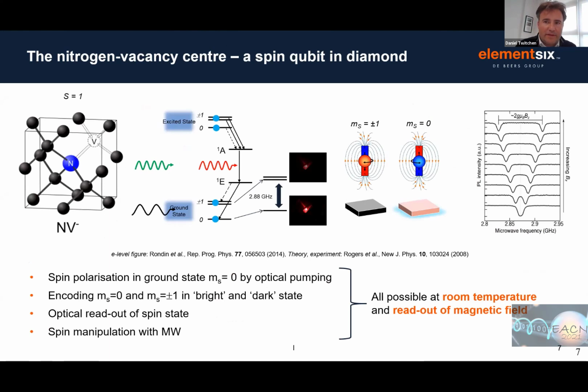So switching quickly back to the NV and talking a little bit about the flavor of the work that we've been heavily involved with over the last 5 or 6 years. As many of you know, this nitrogen-vacancy defect, you can spin polarize at room temperature by shining a green light on it. These states will go up to 1, but some of them will relax back via this singlet state and preferentially populate the 0 state. So you can go around that cycle a few times and optically spin polarize the 0 state. And then with an RF source around 2.8 gigahertz, you can cycle those transitions between the 0 and 1 and produce a superposition state. You can then come back along and interrogate that system, throw another green photon at it, and measure the intensity coming out. Depending on whether it's in the 0 state, where it's brighter, or the 1 state, where it's darker, you've got optical spin readout. So it's very attractive. It's a relatively simple system to initialize and read out, and that's certainly been one of the attractions of it in the early days.